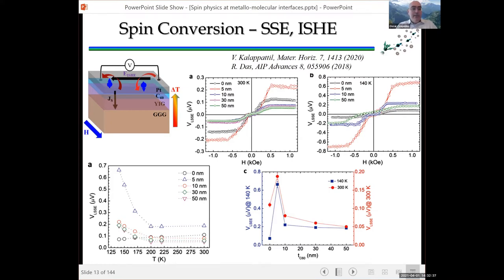And what they observe is that if you do the measurement in a conventional structure, that is YIG, a ferromagnetic insulator, and platinum, you get a spin Seebeck voltage of the order of 0.6, 0.8 microvolts. But if you separate the two layers by 5 nanometers of C60, you can increase this effect by up to almost an order of magnitude at low temperatures. Not so low, 140 Kelvin or so. So again, it seems like the molecule C60 is enhancing the effect that we see in the conventional structure and the metallic, in this case, magnetic oxide.